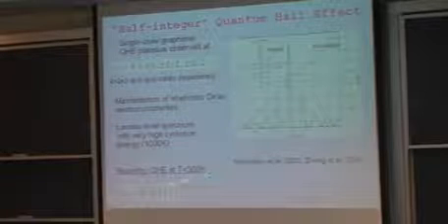Here, 4 arises because you have degeneracy because of the pseudospin, sublattice degeneracy, and you also have valley degeneracy. So there is an extra factor of 4, counting both of them. But this is an integral multiple of 4e squared over h. But the extra feature that comes in is this half. So that's why it is called half integer or anomalous quantum Hall effect. And this arises because of the contribution of the n equals 0 level, because that level has half degeneracy relative to the other levels.